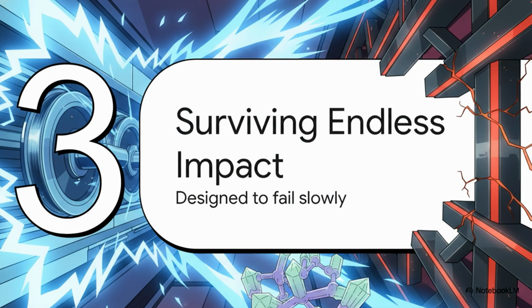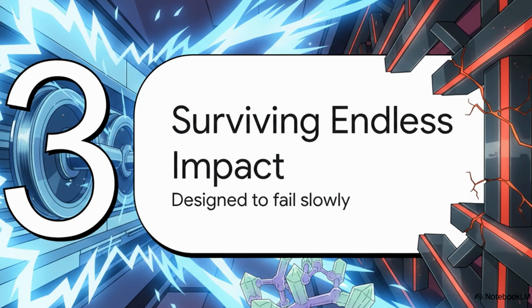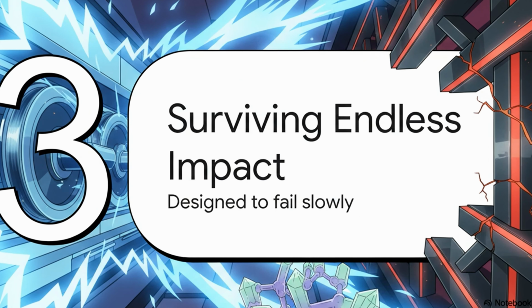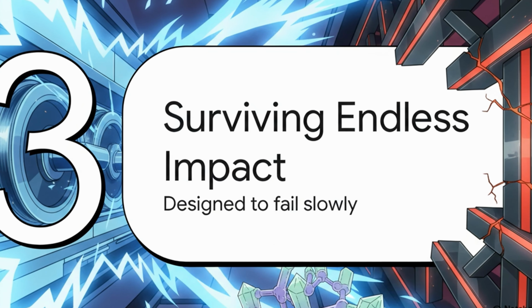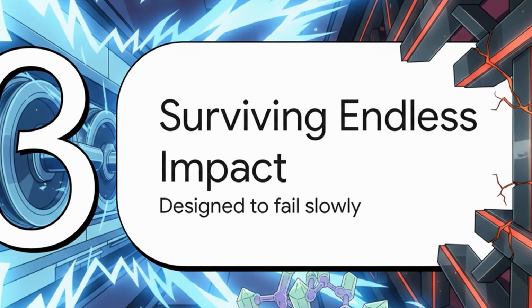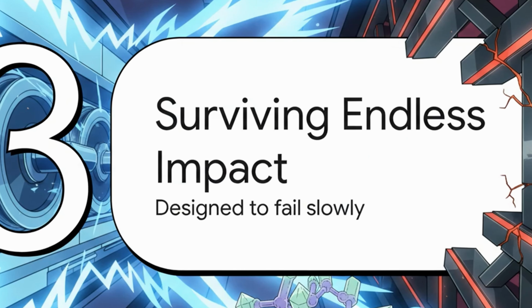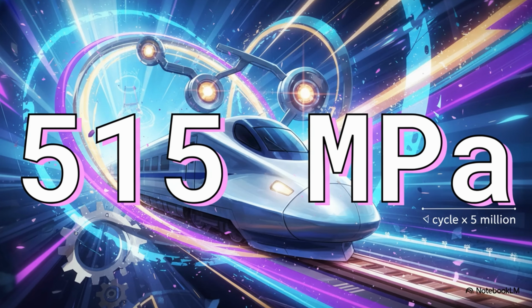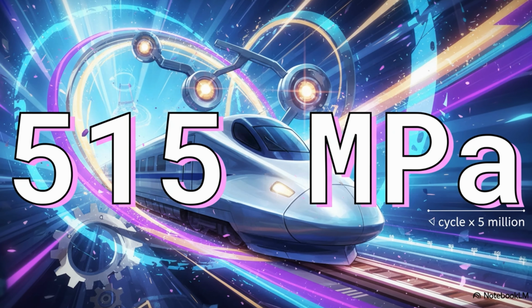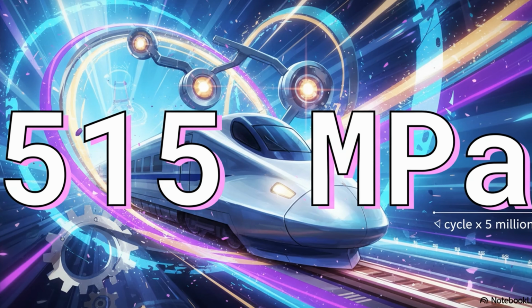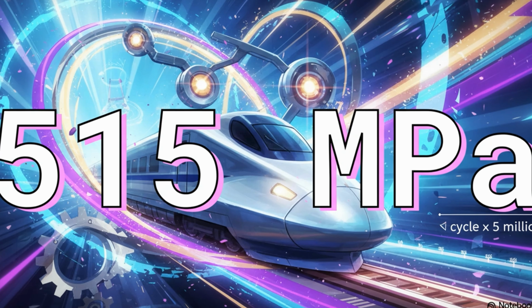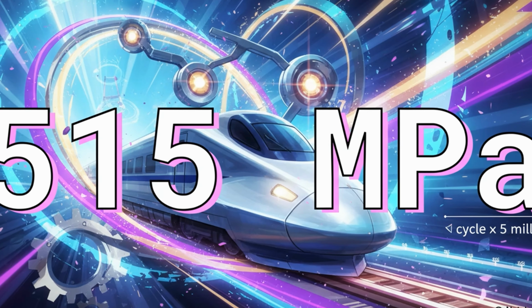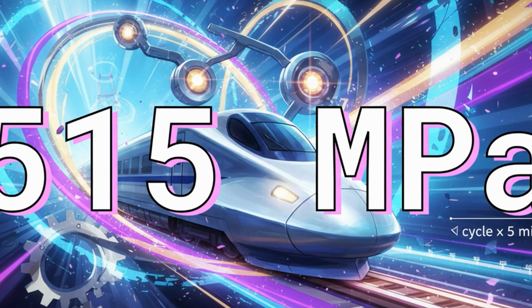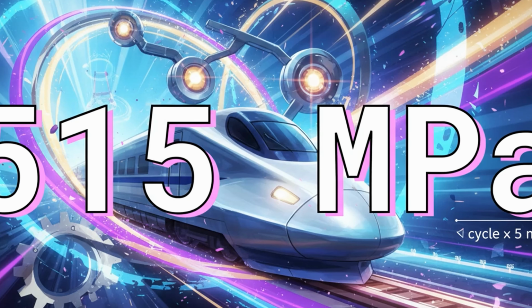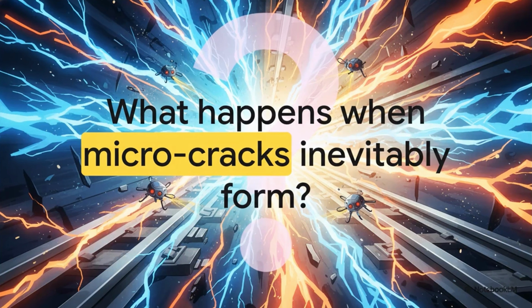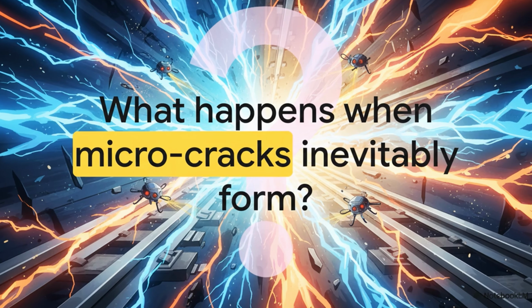But, you know, brute strength is only half the battle. This steel also has to put up with the endless, pounding impact of trains flying by at high speed. So it's not just about being strong, it's about being designed to fail, as slowly as humanly possible. And that brings us to this number, 515 megapascals. That's the steel's baseline fatigue strength. It means it can handle that insane level of stress for over 5 million cycles. That's like 5 million trains passing over it, before it even starts to show the first signs of getting tired. That's just incredible endurance.